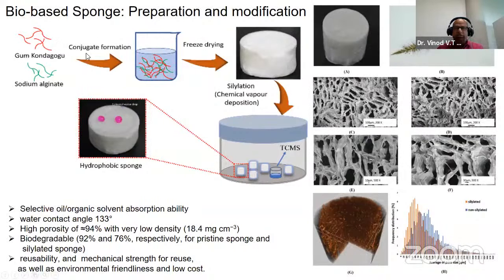In this preparation, we used two important gums: Gum Kondagogu and sodium alginate, mixed together in various ratios and freeze-dried to get a sponge. Both these gums are soluble in water, so the sponge is soluble in water, meaning it's hydrophilic in nature. When you do the silylation, chemical vapor deposition, we could make this sponge a water-insoluble sponge.